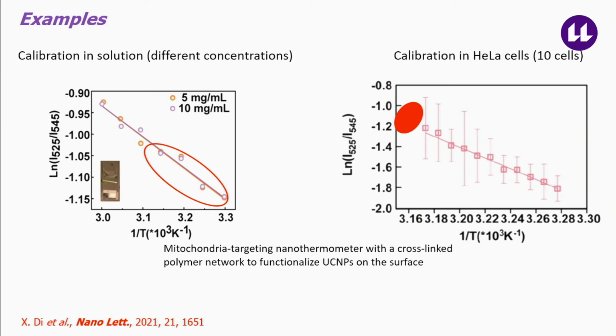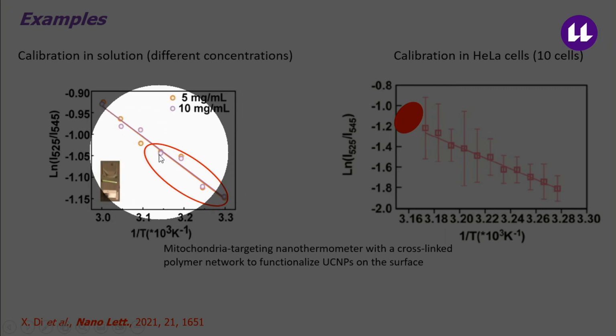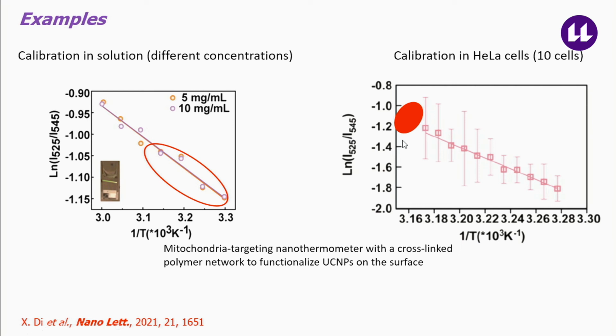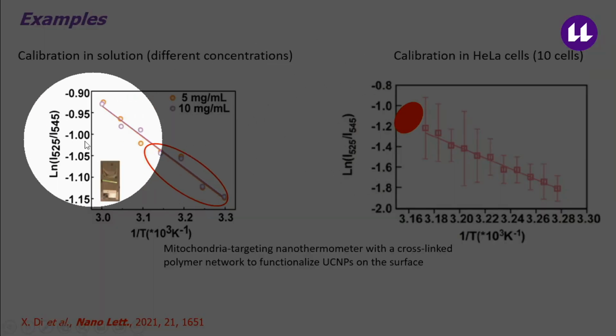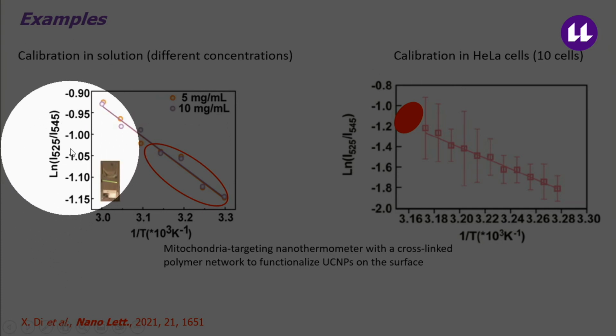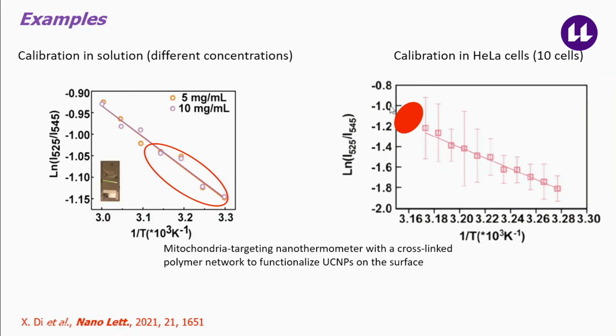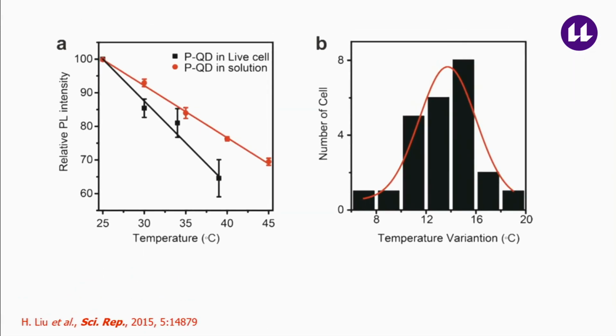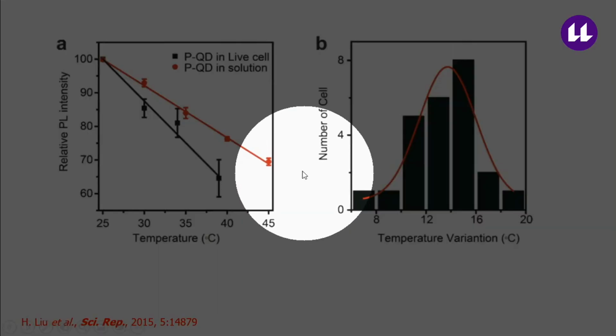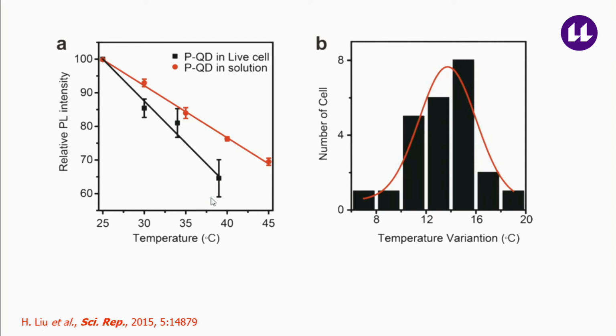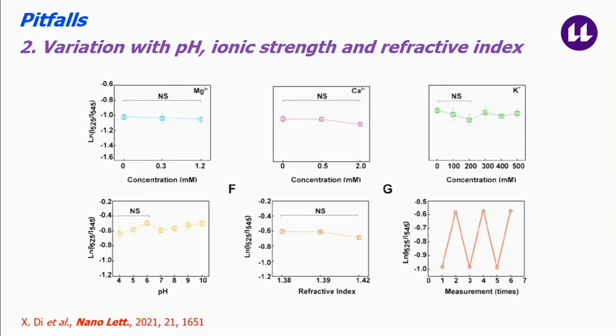So for instance, in this case, this is the calibration curve in suspension, and this is the calibration curve in vivo. And you see, despite the units here, this is the logarithm of the intensity ratio, the values are quite different, okay? Or in this case here, in which they use quantum dots, you can see that the temperature response in a live cell or in solution are quite different. This means that this is a problem or a challenge that needs to be addressed.